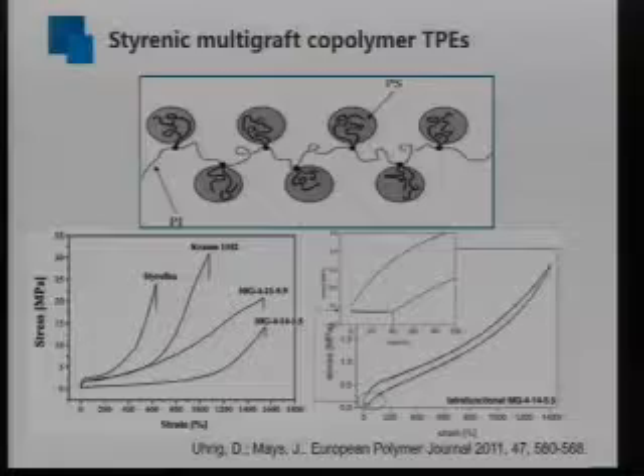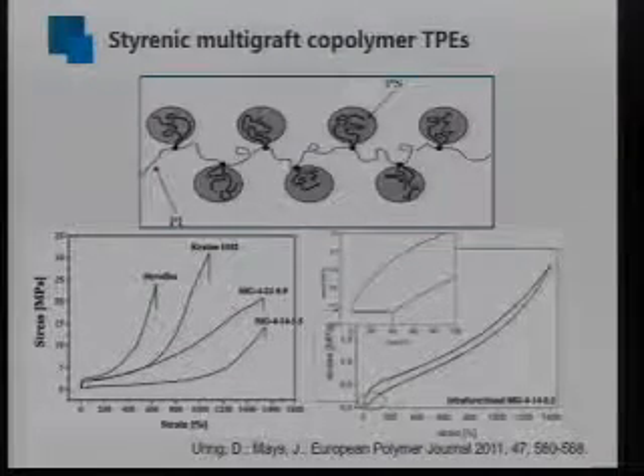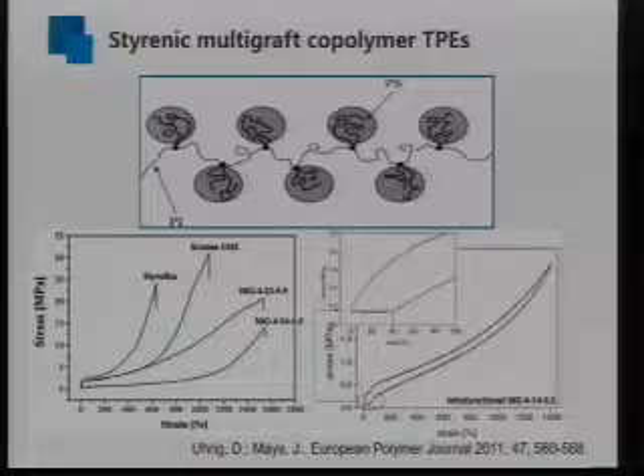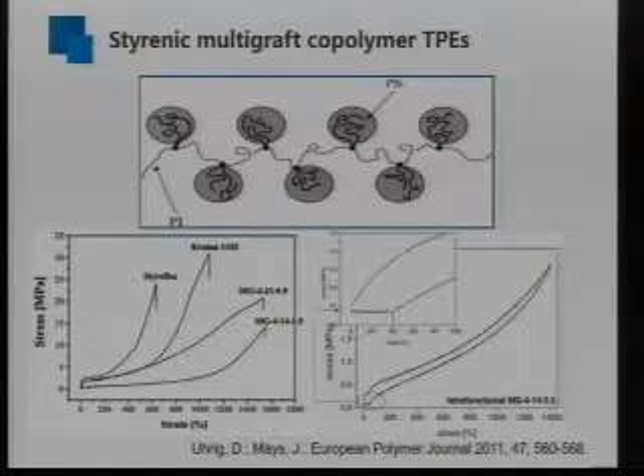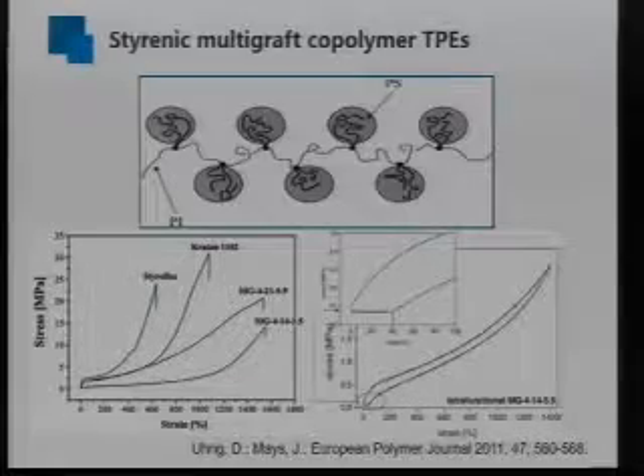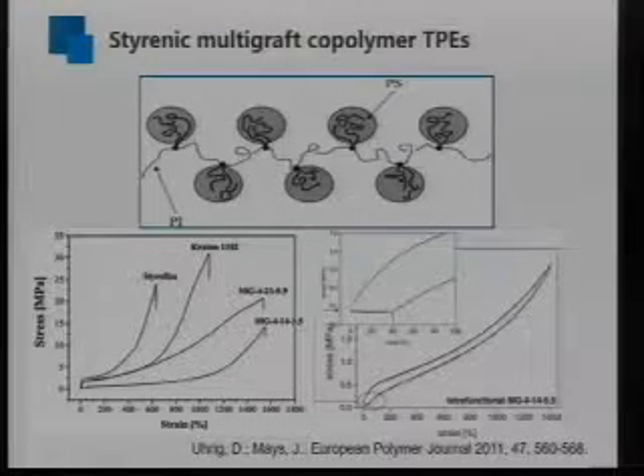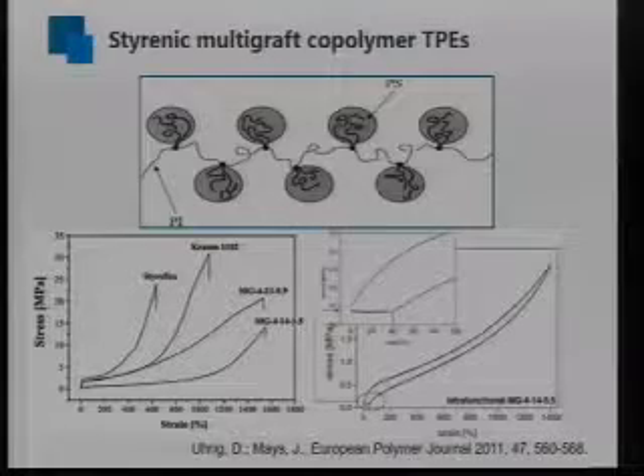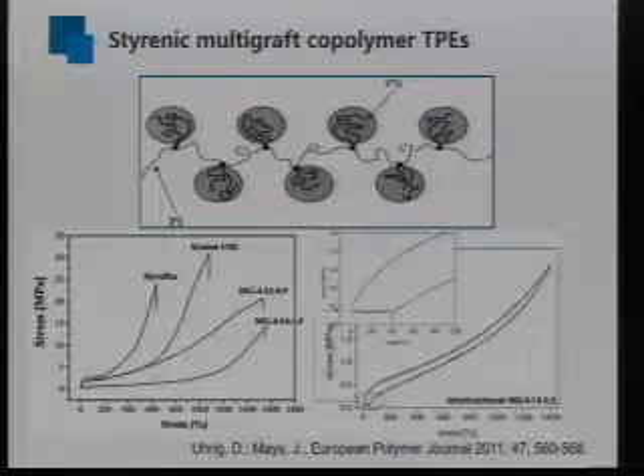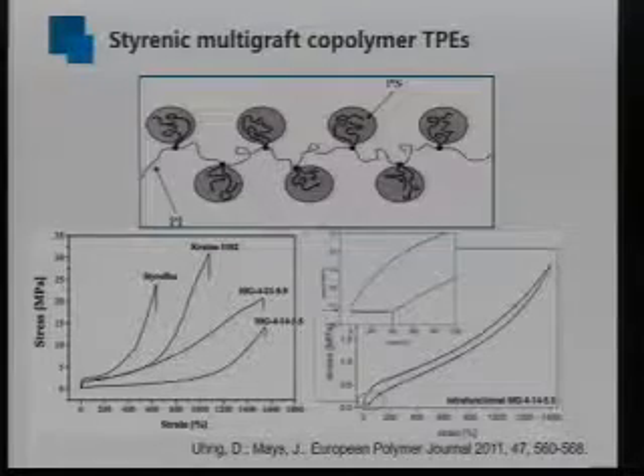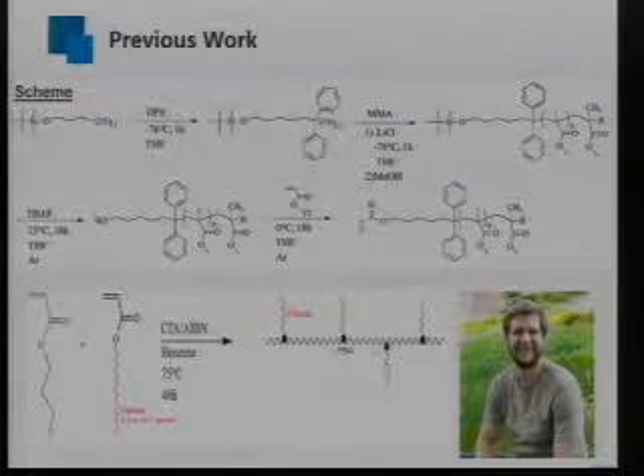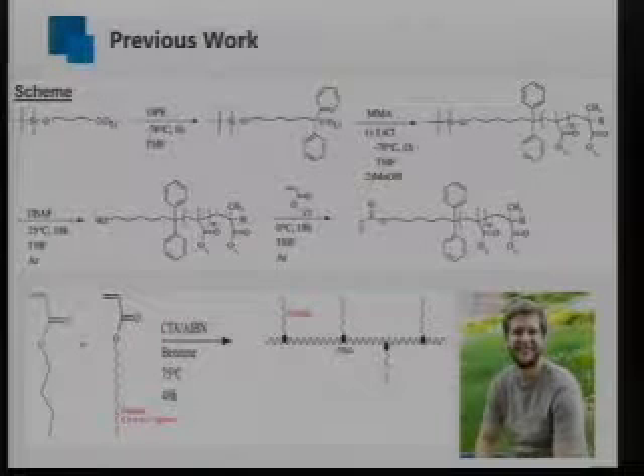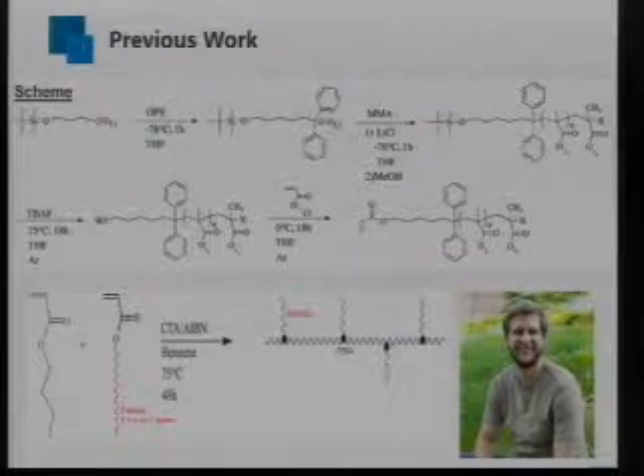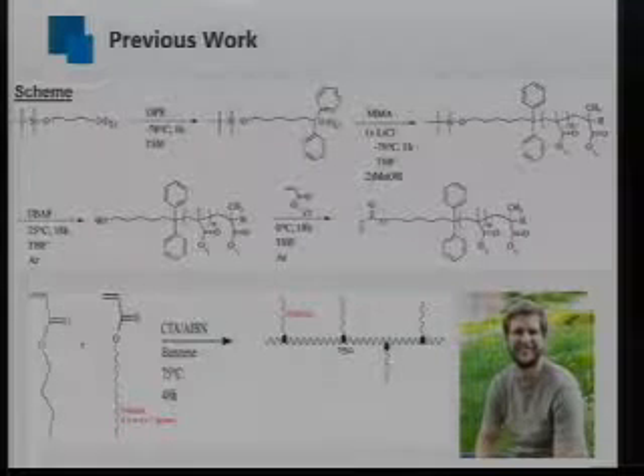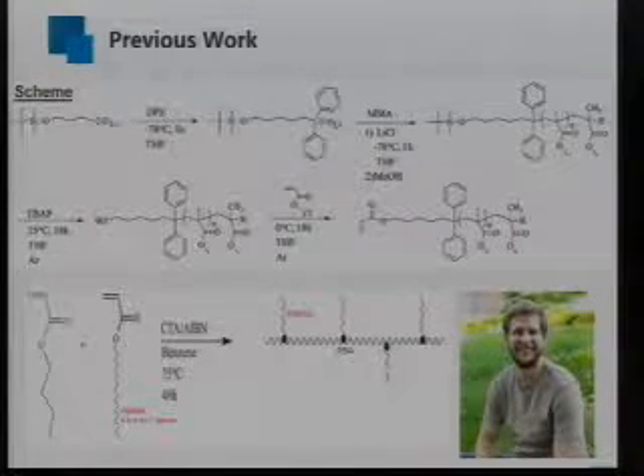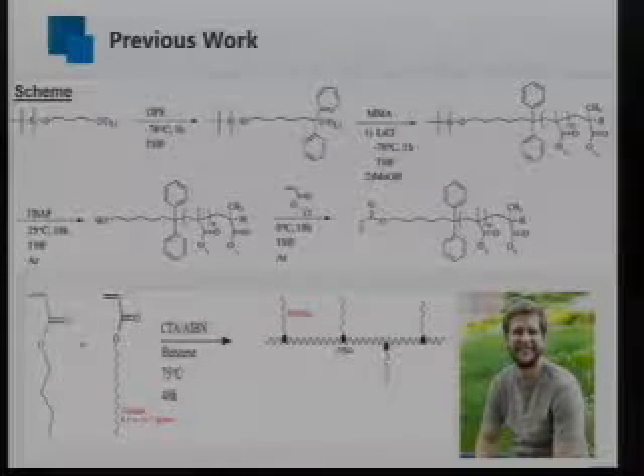And even when this sample was stretched to 14 times, it can still recover to its original shape with only 40% strain loss. So by the combination of this much improved elongation higher than 1,500% and very good strain recovery, they named this material a super elastomer. The preliminary work on acrylic-based thermoplastic elastomer was done by our lab senior, Dr. Andrew Goodwin, using polybutyl acrylate as the main chain and polymethyl methacrylate as the side chains by a graft-through methodology.